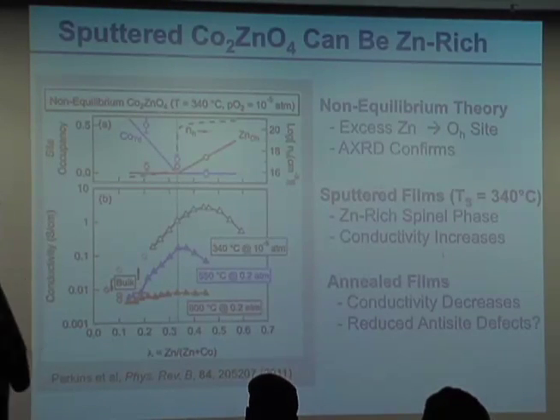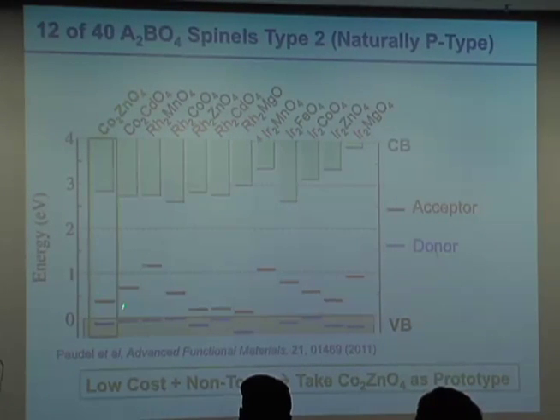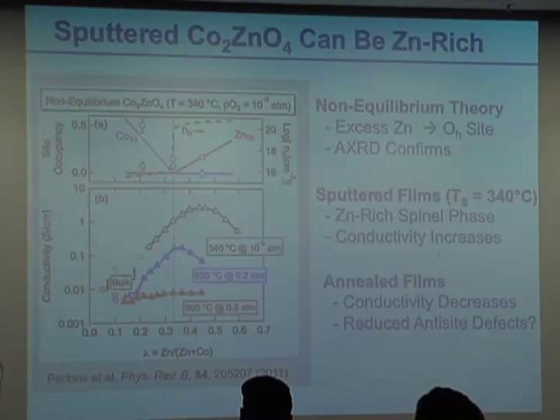One of the first things that we did was to say if we want to make more of these acceptor systems, we need to go zinc rich. So if you look at the theory, if you go zinc rich in this, you start to throw zinc on the octahedral sites, and you would expect the conductivity to increase. Now, as we do that, we've actually been able to see the conductivity increase from below 0.01. If we look at this under equilibrium conditions, it's very hard to make this, and we get a phase separation to a zinc oxide material. But if we look at this on sputtered films, particularly with low substrate temperatures, you see we can get this non-equilibrium growth where we've made these zinc rich and get much higher conductivity than we do in the higher temperature systems.